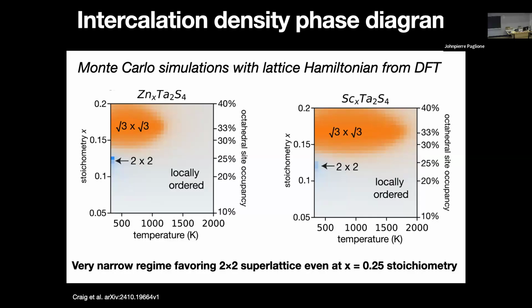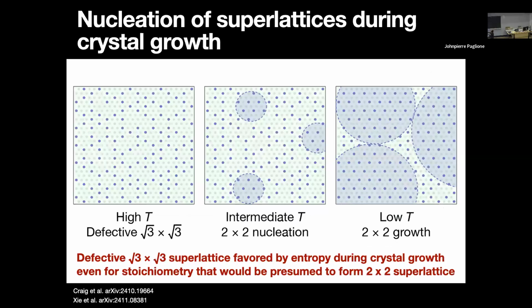So if you're growing at 800, 900, or 1,000, depending on how you cool down, you might trap the system in a mixture of 2x2 and root 3x3. The reason is that at high temperatures in a 0.25 stoichiometry, entropy favors a disordered root 3x3, because it's a configurational thing, right?